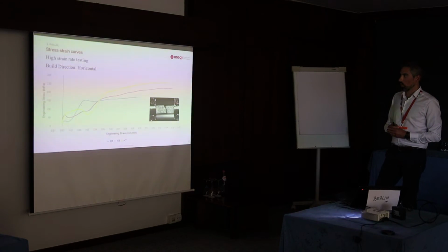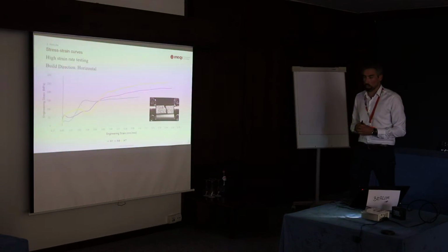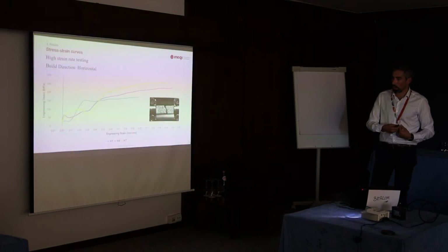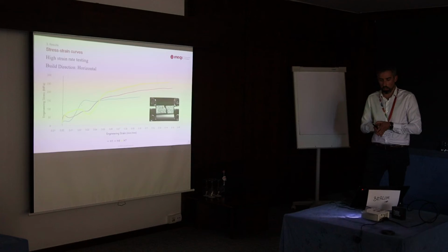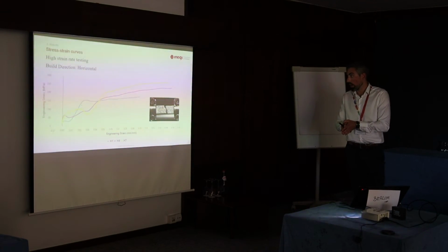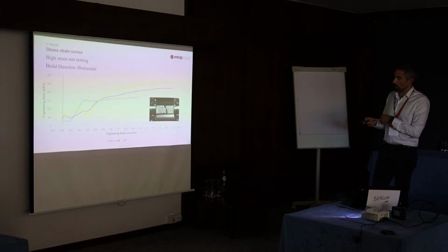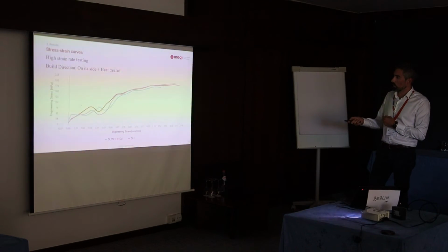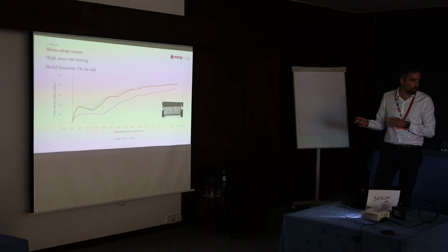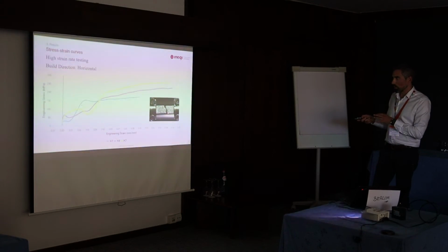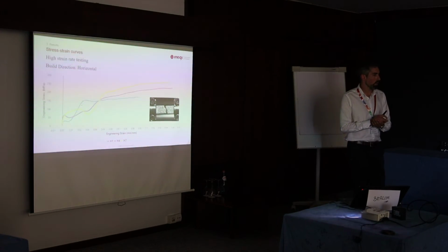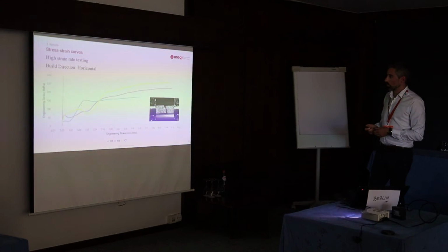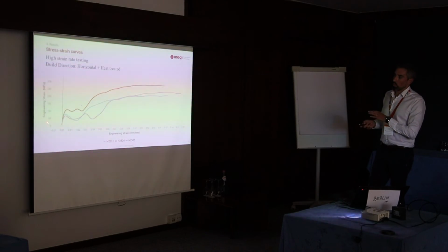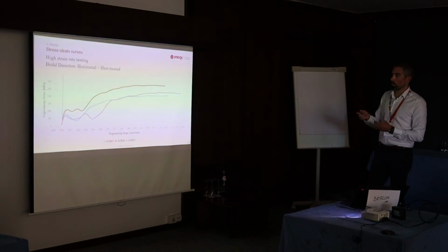The horizontal direction is where we found more scatter of the results. This, of course, has to do with how the specimens are produced and how the wave is propagating along the direction of the material, and it can encounter the inner defects in the material in a different way and propagate differently. Here we would have a much more clear typical fracture. Instead, on the horizontal, we would already have some sort of 45 degrees that the crack would try to make. Again, on the heat treatment, we would see a bit of smoothing on the initial behavior of the material.